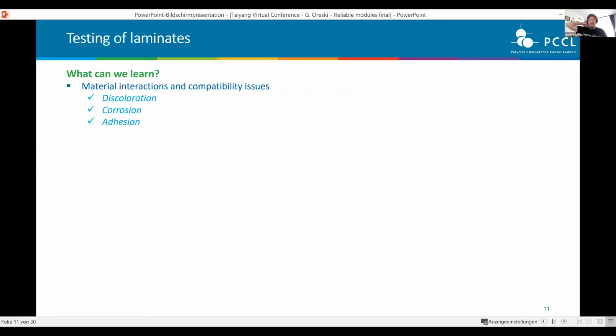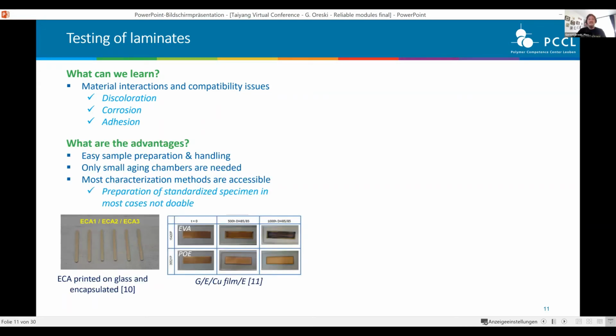Okay, let's go to laminates. So we take a small piece of glass, put in encapsulant, backsheet, and sometimes other components like ribbons or pieces of cell. So what can we learn there? We learn something about material interactions and compatibility issues, like discoloration, corrosion, or adhesion. Advantages, as before: easy sample preparation, only small chambers are needed, and you have most characterization methods accessible, except when you need standardized specimens for mechanical testing, which is a little bit challenging.